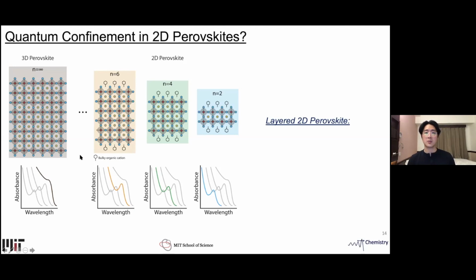So the layered 2D perovskite provides the increase in the band gap, and they are also reported to have better phase stability. That is because perovskite is known to be a soft material, and you could think of these organic cations as blocking the crystal structures in place, thus providing better crystal phase stability.